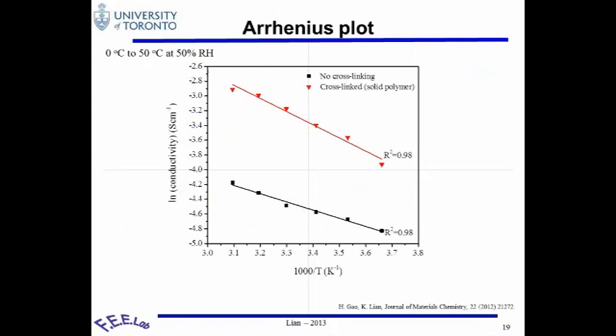And we've also looked at different temperatures, how these electrolytes perform. So far, within the temperature range we look at, this is Gen 2, Gen 3, this one contains small amount of phosphoric acid, this is the cross-linked one. And they are all still within the range of proton hopping mechanism.